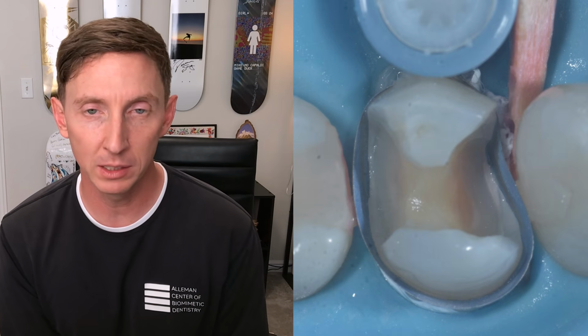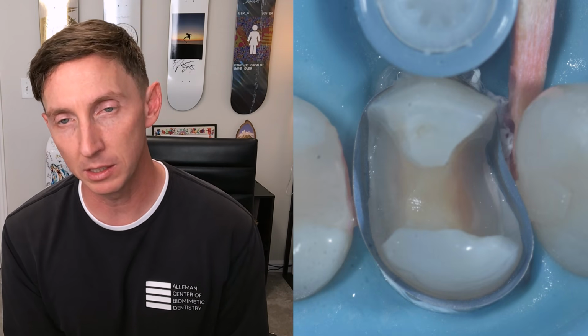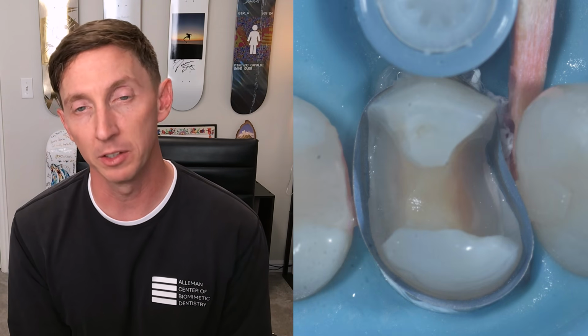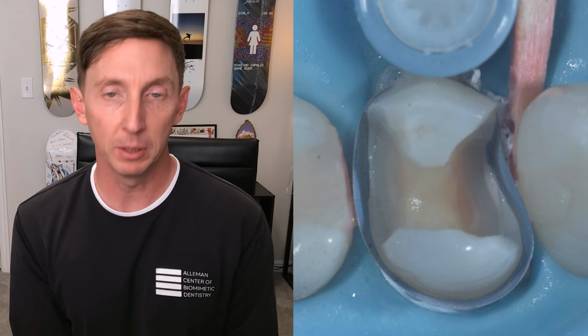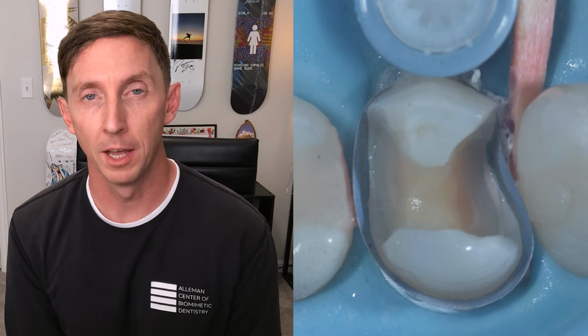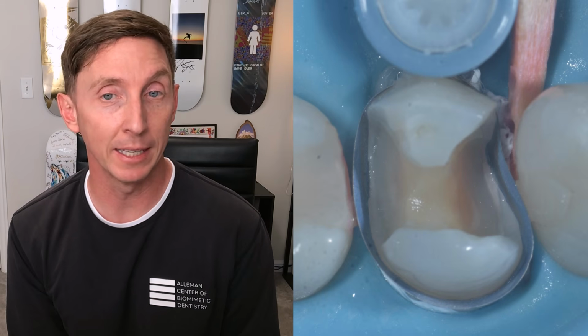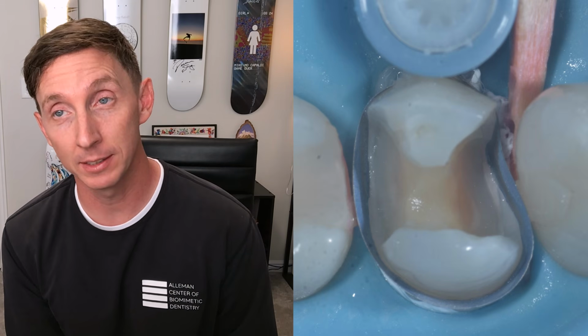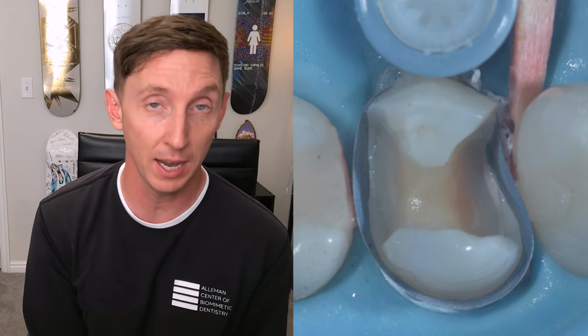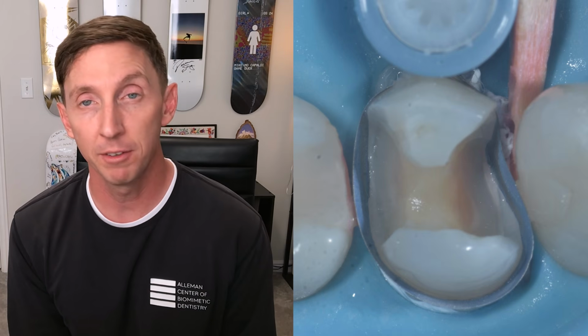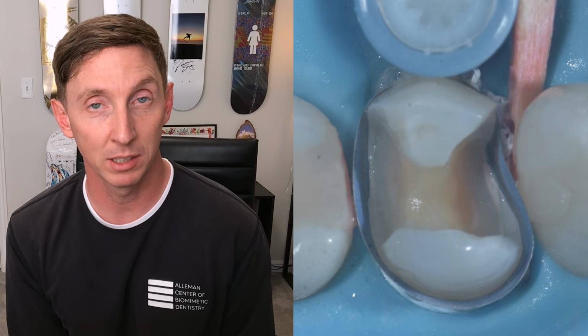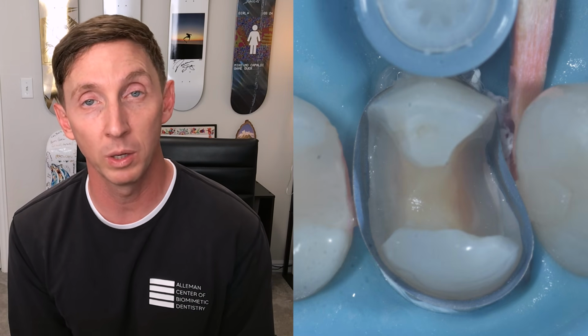Universal bonding systems, the film thickness of the adhesive is actually much less, and there's a potential that you would have no polymerization after curing. Now, this is a point of confusion for many dentists. They will think that the film thickness equates to the thickness of the hybrid layer. Now, if you're using SE Bond or SE Protect, which are the adhesives that I use mainly in my practice, the film thickness is 40 microns, but the thickness of my hybrid layer is only 0.5 microns in total thickness, and this is where we get the strength.